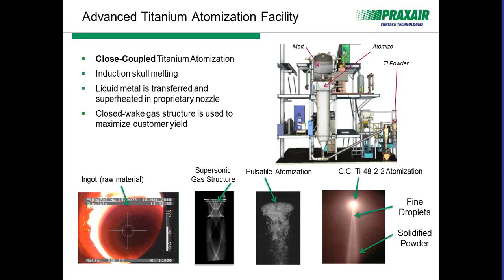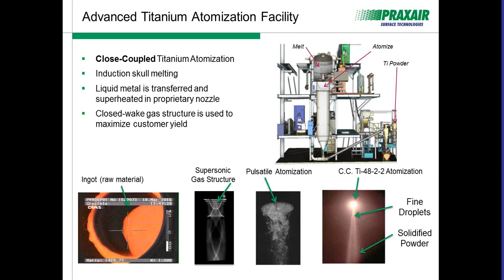And how that works is as it melts, the liquid actually will splash against the side of the wall and it'll freeze, forming a thin little shell of titanium. You then use the induction or the electromagnetic field from our induction power supply to push the liquid off the wall a little bit, but therefore you're holding liquid titanium within a shell of titanium. This actually keeps the titanium very clean. Really, this is the cleanest melting process available, and as I said, it is the industry standard. We then look at transferring that liquid through the nozzle and using a pre-engineered gas structure.